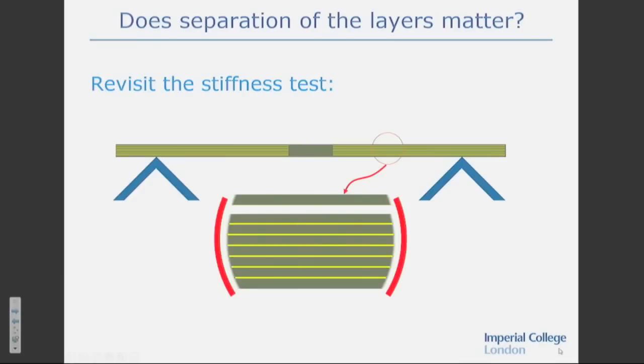Well, we're going to have a look again at this stiffness test. And we're going to look at a different stiffness test now. And this is the reduced width beam again, carbon composite. But in this one, we've separated the plies over here every 0.5 millimeter. Remember I said this was 4 millimeters thick. Well, I've separated into 0.5 millimeter intervals. So now we've got 8 separate laminates there. And of course, because they're separated at each of these yellow boundaries, it means they can separate. Not only move apart, of course, but also slide relative to each other freely. So, let's have a look at this.